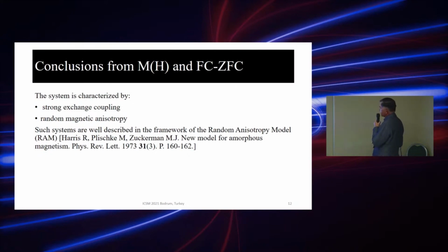So from M versus H and field-cooled, zero-field-cooled measurements, we conclude that the system is characterized by strong exchange coupling and by random magnetic anisotropy. These are two necessary conditions for application of the random anisotropy model.